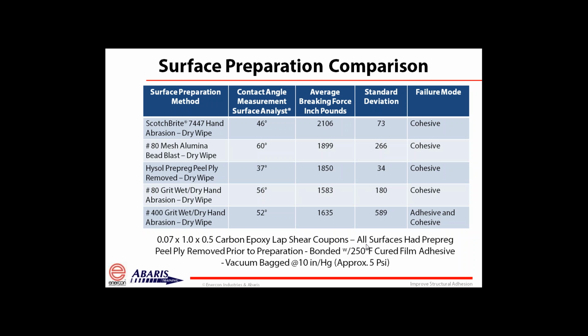They're made with a medium modulus carbon fiber. All surfaces have had a pre-preg peel ply removed prior to preparation. They're bonded with a 250°F cure film adhesive, vacuum bagged at 10 inches of mercury, which is about 5 psi. So you have the effect of vacuum in these results.